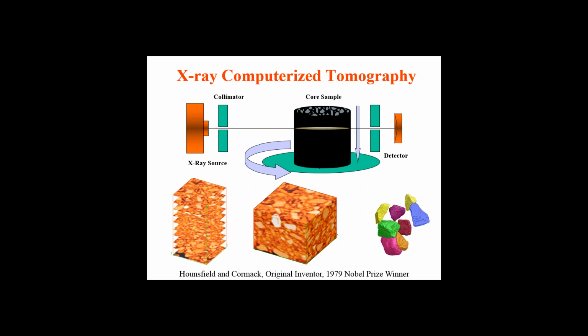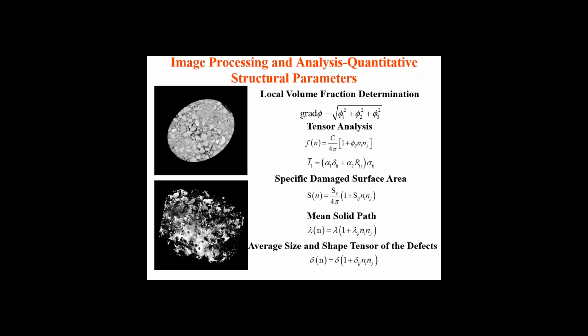And then this reconstruction is like individual particles. Later on I will talk about this one as well. If you can reconstruct a three-dimensional representation of individual particles, you can then use these particles in the modeling of the discrete element approach. And the first step, if you have the structure, then you may use parameters like damage surface area, damage tensor, the spacing among the voids, or this type of geometry, to represent the material structure in a statistical kind of approach, right? And to link these parameters, some of the defect parameters, to the material performance. So that's one stage we can achieve.